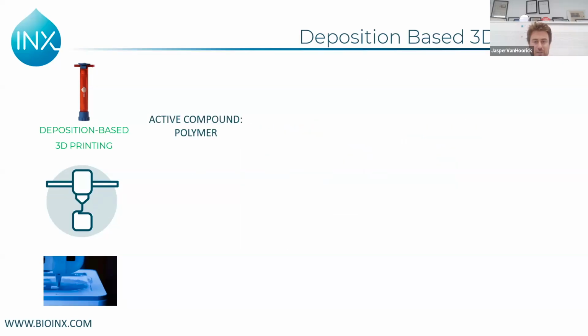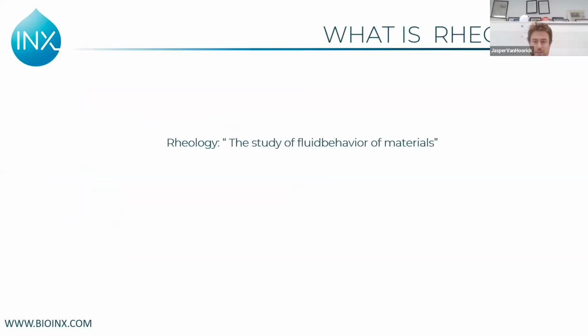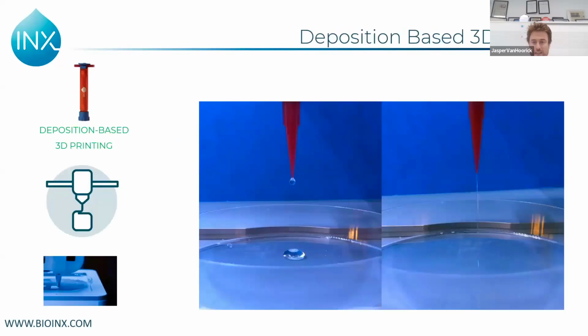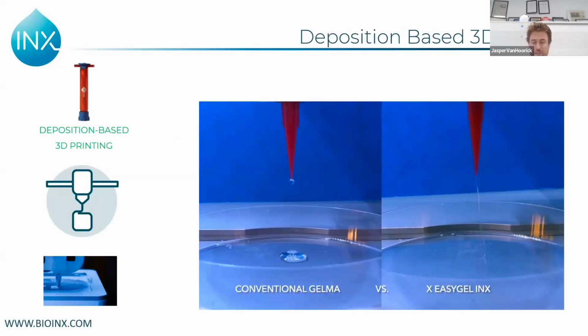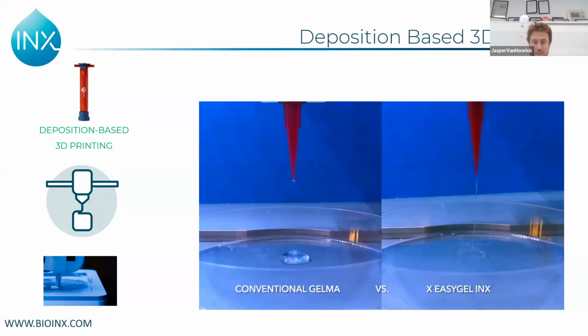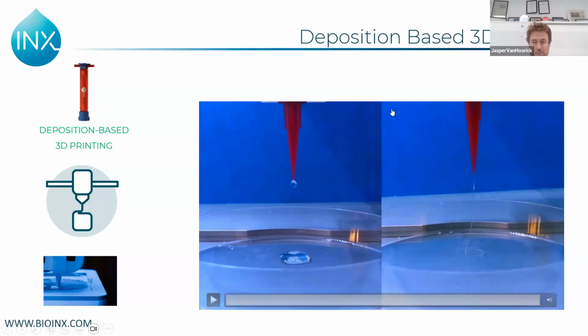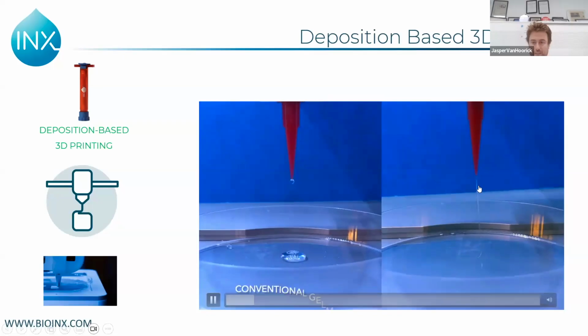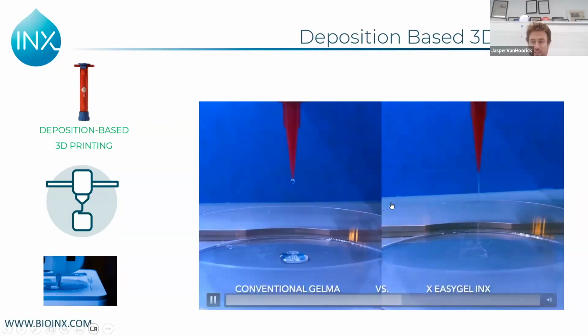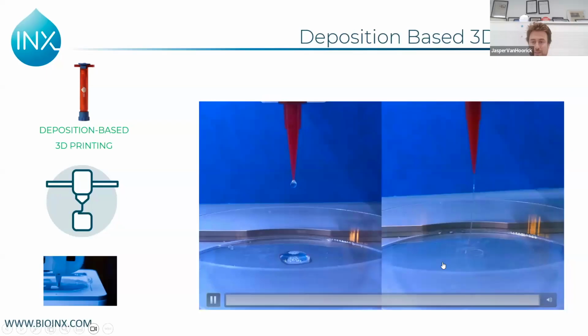And how do you get there? Your active compound in your bioink is always your polymer that will determine your main properties of your material after printing. But in this case, we add a rheological modifier to it. And a rheological modifier is actually a modifier which modifies the rheological behavior. And rheology is the study of fluid behavior of materials. And by adding some of these rheological modifiers, we can, for example, go from conventional GelMA solution, which is unprintable at 37 degrees, to a nicely extrudable material which has shear thinning properties and keeps its nice filament shape after deposition.